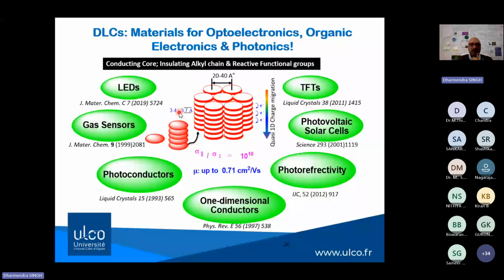In these molecules, they have the conducting or semiconducting core and the alkyl chain, which is just an aliphatic chain like CnH2n+1, and it will be insulating in nature, and they will have some other functional group as well, making them electron-deficient or electron-rich in character. If you talk about the geometry, here you could see that the distance between two consecutive columns is around 20 to 40 angstrom, and the interdisk space is between 3.4 to 3.7 angstrom.